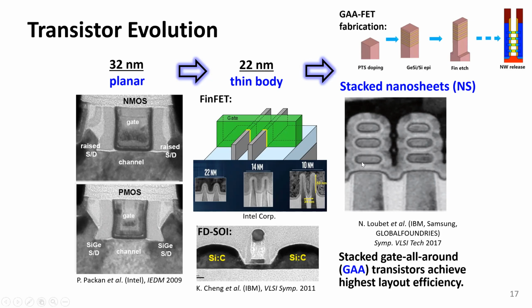Now, in order to form this complex stack, we start with the silicon wafer, but we have to grow epitaxially layers of silicon germanium, and then silicon and silicon germanium, and so on. So you have to grow a stack of semiconductors, perfectly epitaxially with no defects, before you pattern the semiconductor into tall fins and continue the fabrication process. And eventually, later during the fabrication process, you selectively remove the silicon germanium layer. It's a sacrificial layer to form air gaps, and then you can form the gate dielectric and the gate material stacks to wrap all the way around these nanowires.